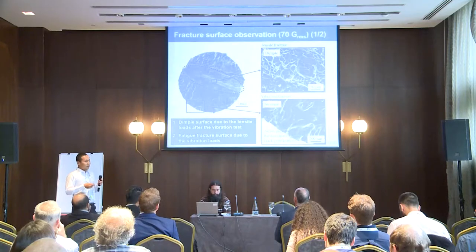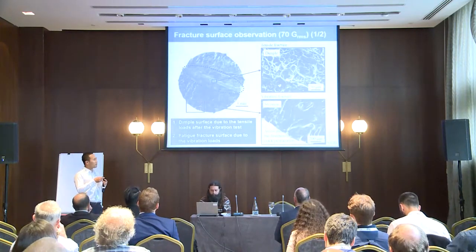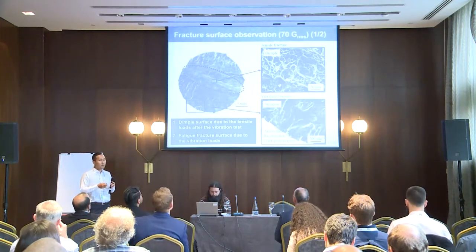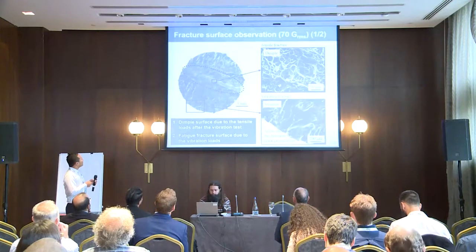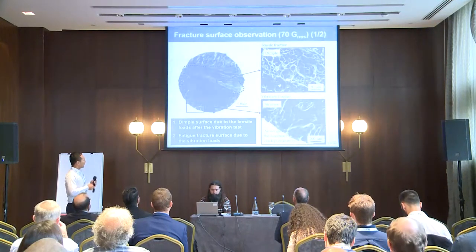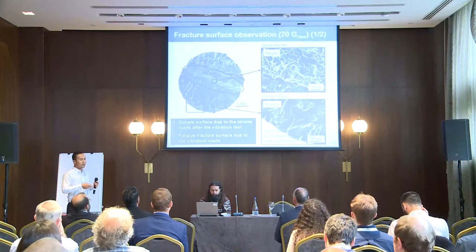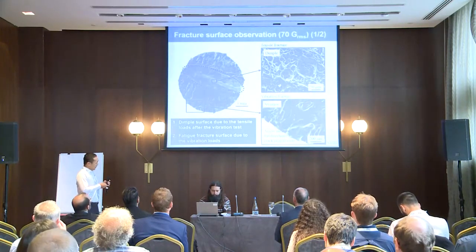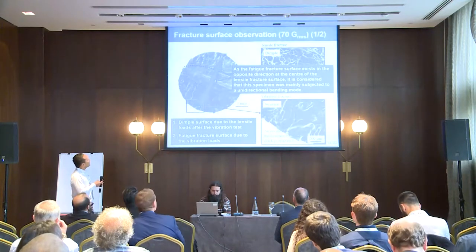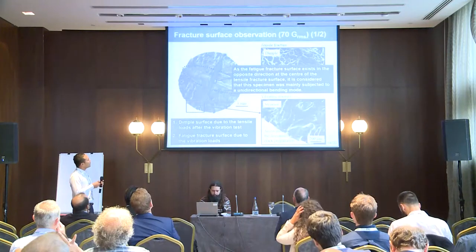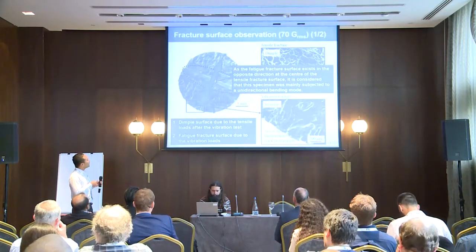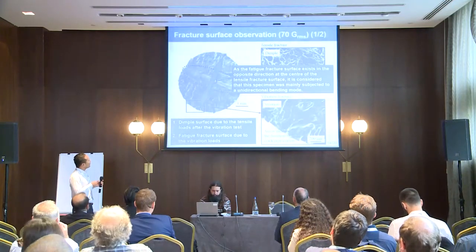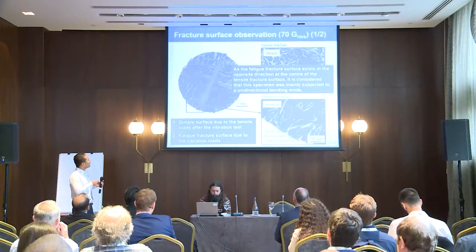After observing the surface, we fractured the specimen using a tensile test and observed the fracture surface. You can see two types of surface: one is a dimple surface due to the tensile fracture after the vibration test, and the second is the fatigue fracture surface due to the vibration loading. The fatigue fracture surface exists on the opposite side from the center of the tensile fracture surface. Therefore, it is considered that the specimen was mainly subjected to unidirectional bending mode.